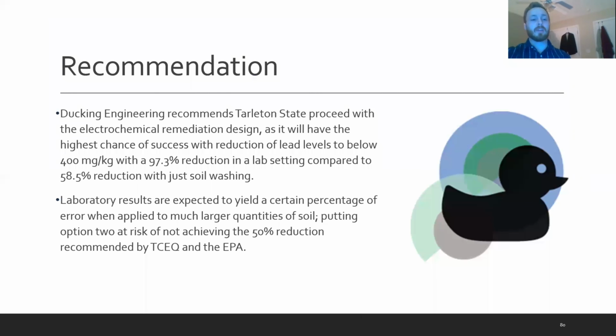Based off of this, Ducking Engineering recommends that Tarleton State proceed with the electrochemical remediation design, as it will have the highest chance of success with the reduction of lead levels below 400 milligrams per kilogram, with a 97.3% reduction, compared to only 58.5% with just the soil wash. Now, it should be noted that these are laboratory results, and they should expect to yield a certain percentage of error when applied to much larger quantities of soil, which could possibly put option 2 at risk of not achieving the 50% reduction recommended by the EPA.